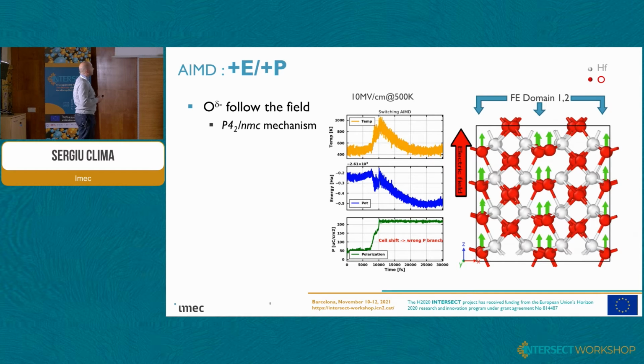First it goes with the tetragonal mechanism, which has a low barrier, but then the polarization switches from the plus P to the minus P. And then we have some interesting things going on there, like, for example, half of a unit cell shift. So the dipoles already switched to the next row of atoms, so the tetra-coordinated oxygens become three-coordinated and three-coordinated become tetra-coordinated.